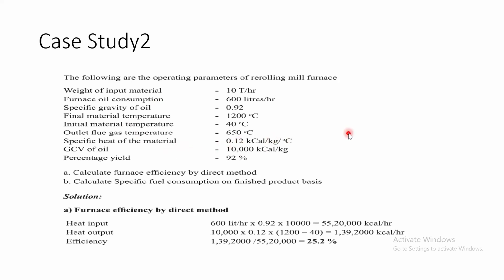So specific heat of the material is 0.12 kilocalorie per kg per degree centigrade. GCV of oil is 10,000 kilocalorie per kg and percentage yield is 92%. So ultimately yield is related to the material being used. Now considering specific gravity as 0.92, you can take heat input is equal to 600 liter per hour into 0.92, which gives you kg per hour, and then heat input is equal to mass of fuel into GCV. GCV given to us is 10,000 kilocalorie per kg. So ultimately heat input is nothing but 600 into 0.92 into 10,000, which is equal to 55 lakh 20,000 kilocalorie per hour. So this is about heat input.